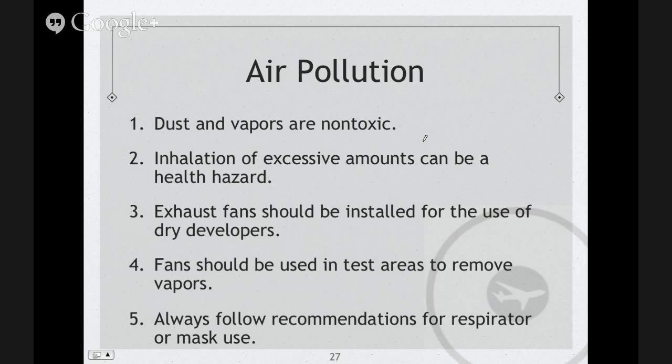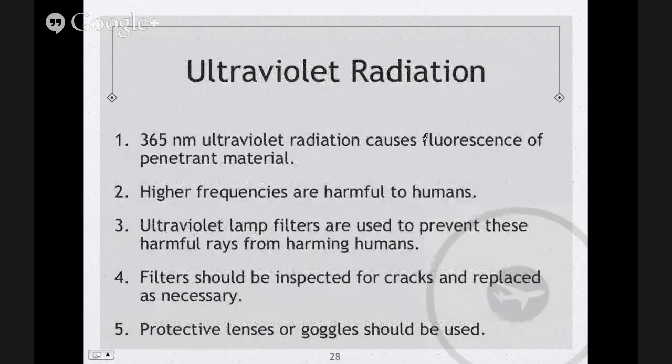So ultraviolet radiation, right? This is the radiation, or the frequency, the wavelength, that our flashlights or our fluorescent ultraviolet lights are going to emit, right? These lights have a wavelength of 365 nanometers, right? And at this frequency, they cause the penetrant to fluoresce, right?